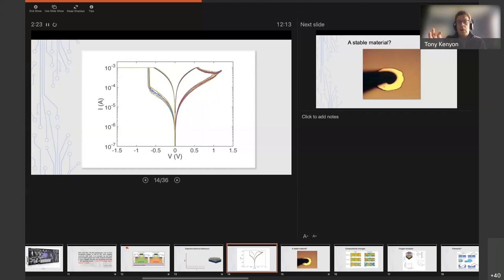So really, you're limited to a relatively small number of oxides. So essentially silicon, hafnium, maybe tantalum oxide, maybe titanium oxide. All of those show resistance switching. All of those show very nice behavior. One of the advantages of silicon oxide, not only is it the most easy to integrate, but also because the band gap of silicon oxide is very wide, it's about 8 or 9 electron volts, it means that the resistance states are very stable. There are one or two other advantages as well, but it's a nice material to choose. But people have looked quite extensively at hafnium and tantalum oxide, and there are technologies based on some of those out there. I hope that answers your question.